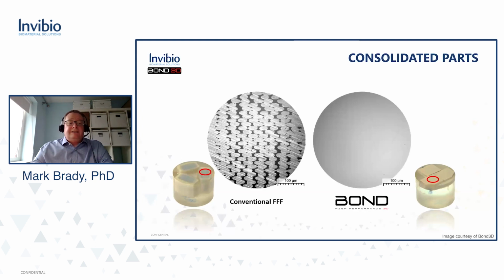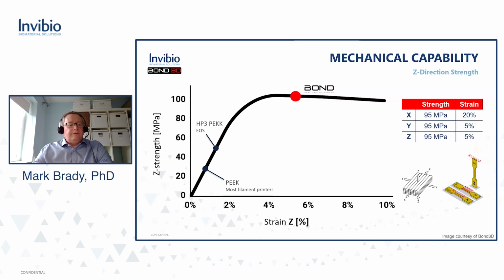Under microscopy, you can really start to see the effect that has on the presence of voids. On the left-hand side, you've got the conventional fused filament fabrication, and on the right-hand side, the consolidated parts that are achievable with the Bond 3D technology when the pressure control printing is deployed. Here on the right-hand side, you're meeting void levels which are comparable with injection molded parts. When we look at how that translates, all of this goes across to excellent mechanical properties, isotropic strength in tensile, including in the Z direction, which is really the Achilles heel when it comes to fused filament fabrication, and the most challenging direction to get high strength with PEEK.